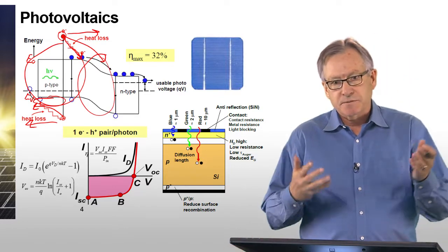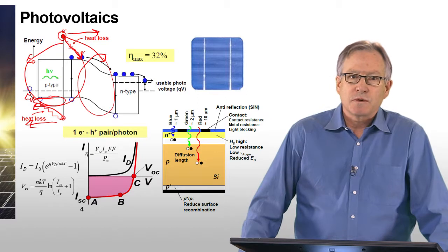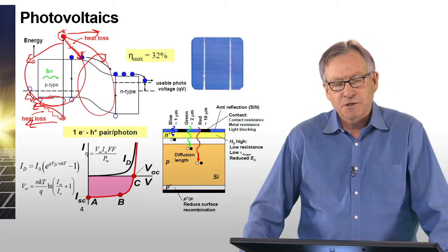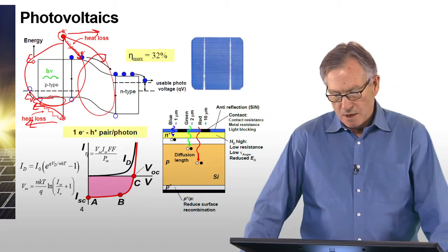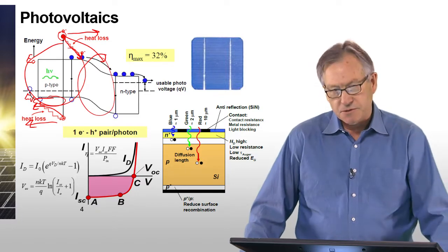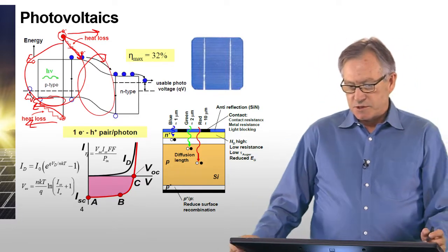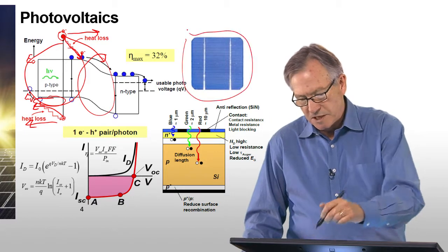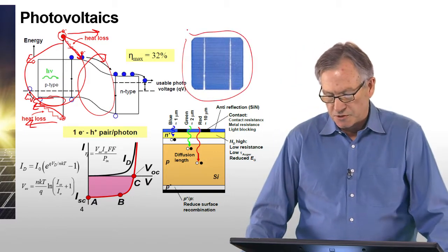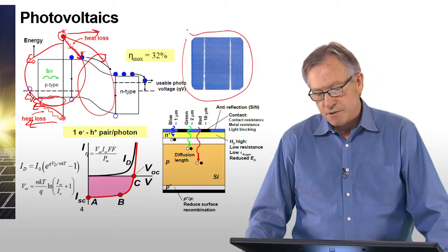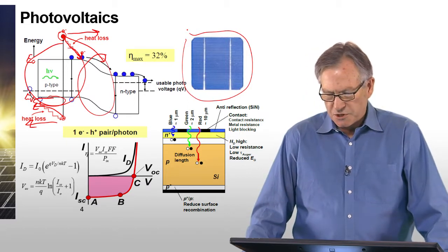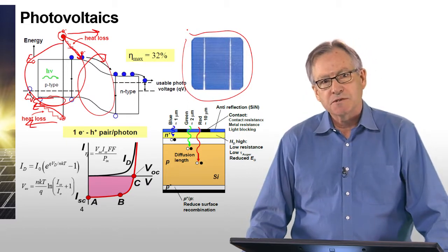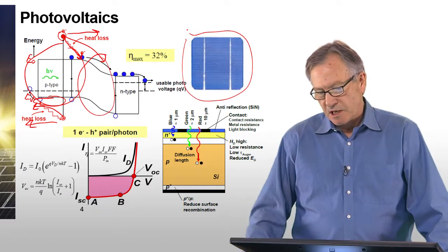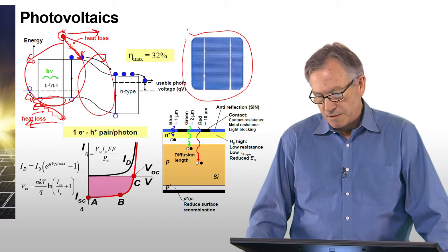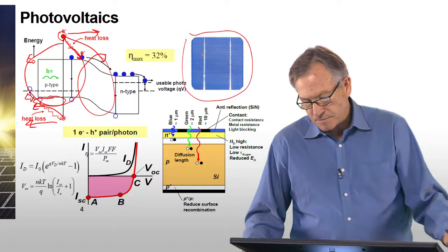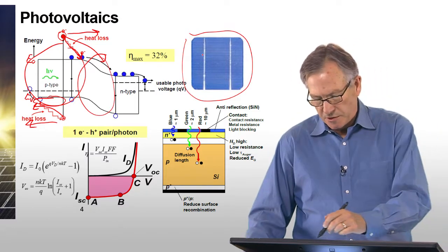So that's the basics of how electron-hole separation occurs and how you get a photocurrent. What's shown in the other pictures are implementations of a solar cell. This over on the right shows the top view of a commercial silicon solar cell. What you can see is it looks kind of bluish in color, and that's because there's an anti-reflection coating that helps to reduce the reflection off the surface. And you can see a metal grid line. And the purpose of that you can see in this picture.